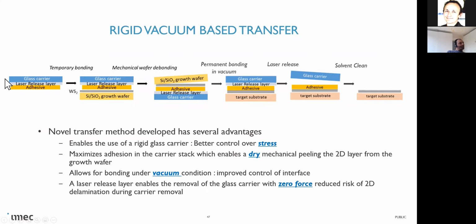So we are using a glass carrier, with an adhesive and a laser release layer. We are mechanically debonding the 2D material from the growth wafer, and then we are doing a bonding step in vacuum. The bonding step in vacuum is there to control basically the interface. And then we are doing a laser release.